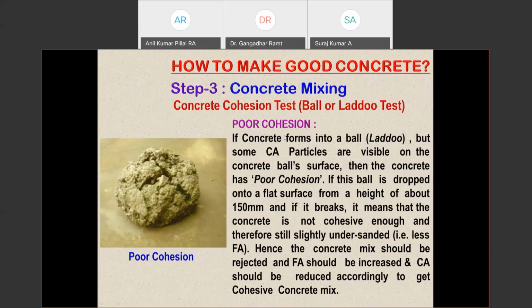For a concrete, we will say poor cohesion is when the concrete forms into a ball, laddu, but some coarse aggregate particles are visible on the concrete ball surface. Then the concrete has poor cohesion. If this ball is dropped onto a flat surface from a height of about 15 centimeter, 150 millimeter, 6 inches, on a tabletop, and if it breaks, it means that the concrete is not cohesive enough and therefore is still slightly undersanded. It is undersanded or has less fine aggregate. Hence, the concrete mix should be rejected and fine aggregate should be increased and coarse aggregate should be reduced accordingly to get a cohesive concrete mix. So, this is the second, for poor cohesion.